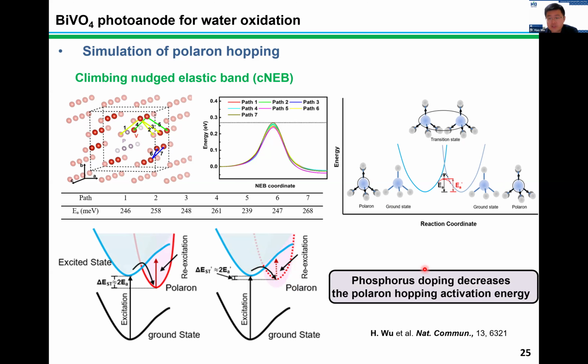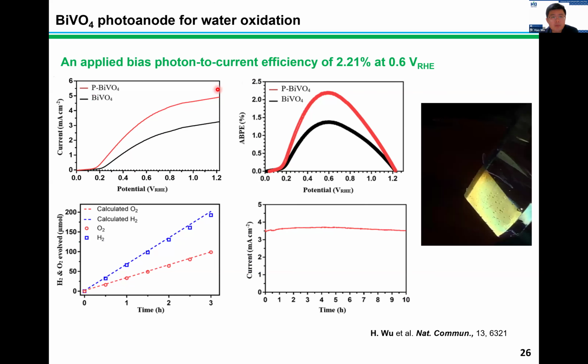And by this polaron engineering, we achieved top performance for photoelectrochemical water splitting with an applied bias photocurrent efficiency of 2.21% at 0.6 volt versus RHE, which is one of the best performances that have been reported in 2022 or before. And with the performance, we can have a look at the recorded video. Upon the light illumination on the bismuth vanadate, we can see its surface shows a robust water oxidation process. So this is about our first study on polaron.